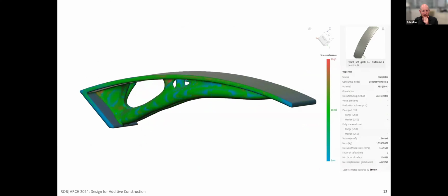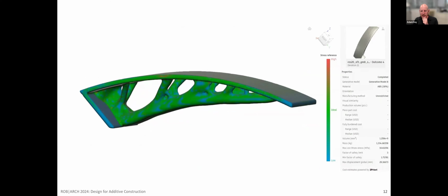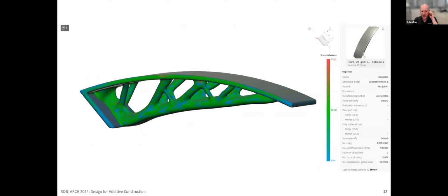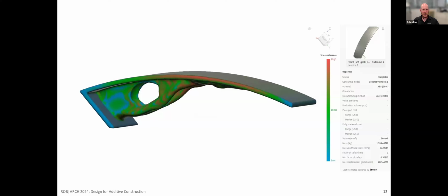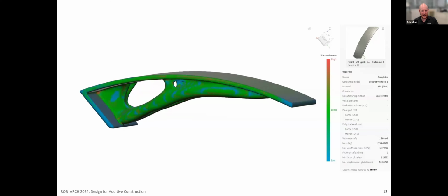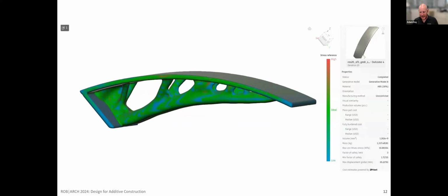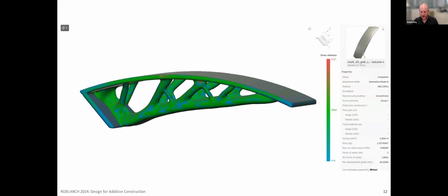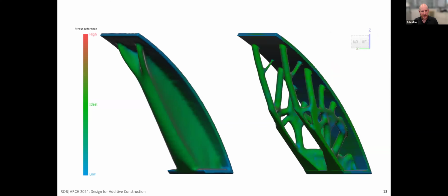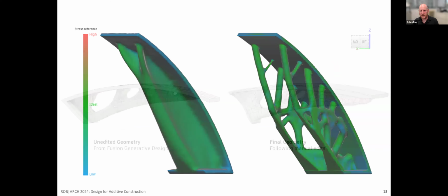This is a little video of the generative design software running. So this is the iterations it's creating. So how it's going from the initial shape and then removing material and then finding that areas are too weak and then adding material until our final study. So you can see a stress reference, high being red, blue being low. So we're able to get a pretty thinned out structure with very low stress, which is kind of cool.